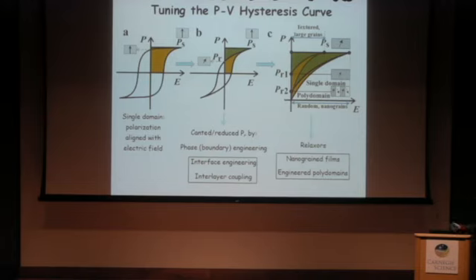So if you want to change this hysteresis loop, let's say we still make the film homogeneous, a single phase, single domain film. You want to get some type of different PV loop. You can change the phase, right? You can change it from tetragonal to rhombohedral. So now you apply a 001 electric field. Eventually, your polarization can align more with the electric field, so you have a big difference between the remnant and the saturated polarization. That's the intrinsic way to do it.